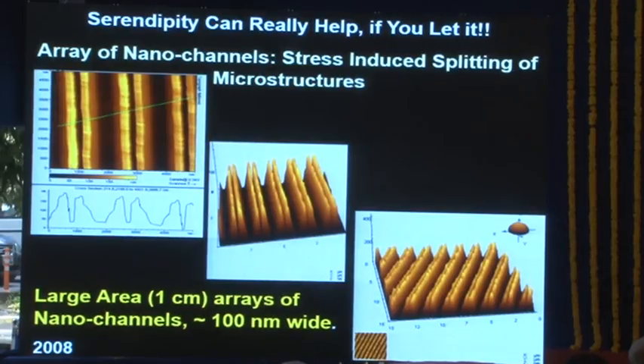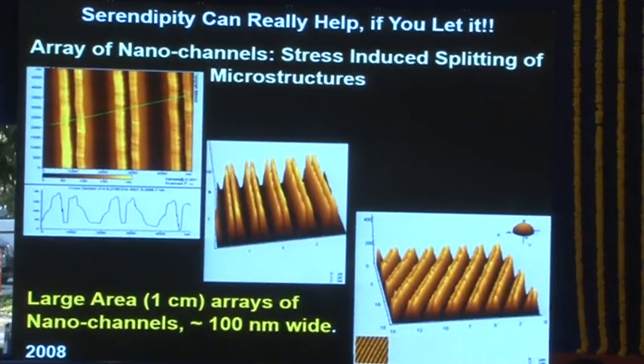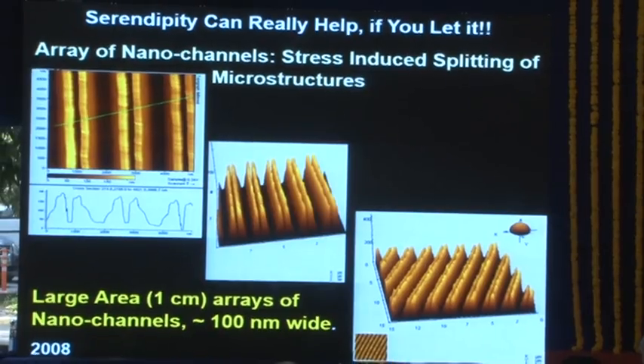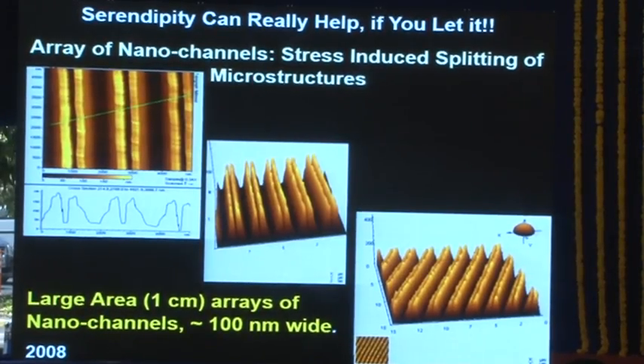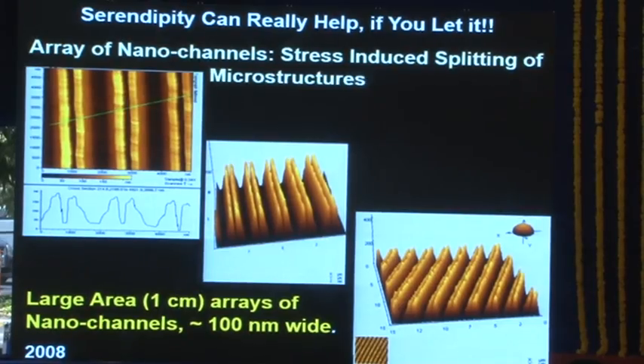For example, stretching out a big molecule, so it's flowing inside the channel, and it would stretch out so you can read it, for example, DNA. So without going into the details of that, what I want to illustrate is that when we're doing something, we should be watching out for what is happening there rather than impose my own ideas and will on what ought to happen there. And then we find some new ideas, we find some new leads, and they may even be more useful than what I started out doing. So don't throw away samples. If things are not as expected, then look, probe more deeply. Of course, most of the time there is some silly reason because of which it's not working. But beyond that, sometimes there are profound things that ought to be captured.